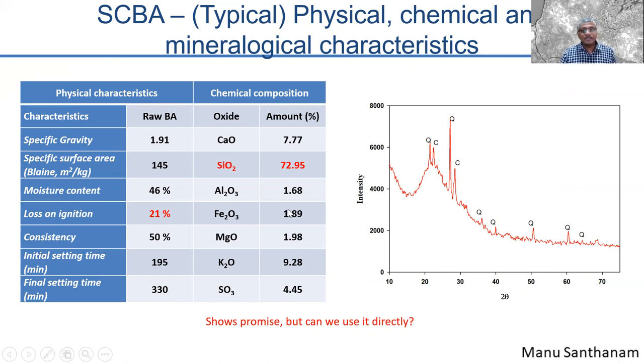The difficulty in trying to use it directly is that you have an extremely high loss on ignition. You see here, the loss on ignition, that means what happens if you burn it to 1000 degrees Celsius, you still lose a lot of weight. And why is that weight going? Because you still have unburned carbon present in the bagasse ash. So about 21% of this material is getting lost on ignition. That means you have so much carbon present that is getting burnt off when you burn it to 1000 degrees Celsius. So what do we do about this?